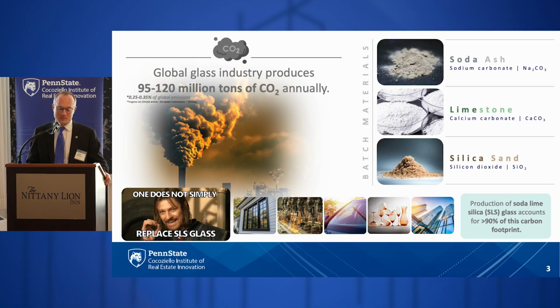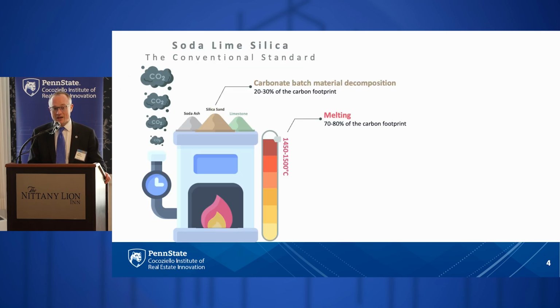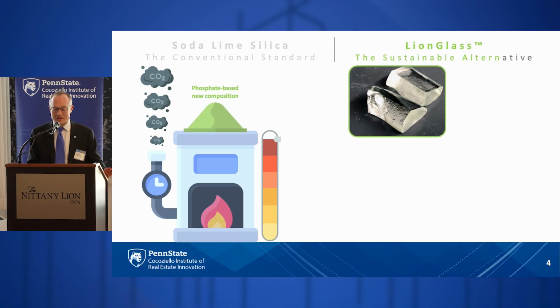Now, the reason that soda lime is called soda lime glass is that two of the main ingredients are soda ash and limestone. These are both carbonates, sodium carbonate and calcium carbonate, and when they melt, the carbonates decompose into oxides, and they release CO2 in the process. So that is about 20 to 30% of the carbon footprint of the glass industry. The remaining 70 to 80% is due to the high temperatures from melting of the glass. This requires temperatures of about 1450 to 1500 degrees Celsius, so very high temperatures.